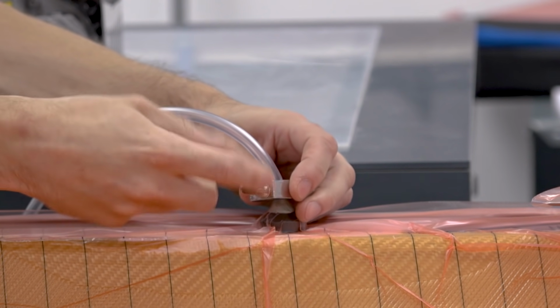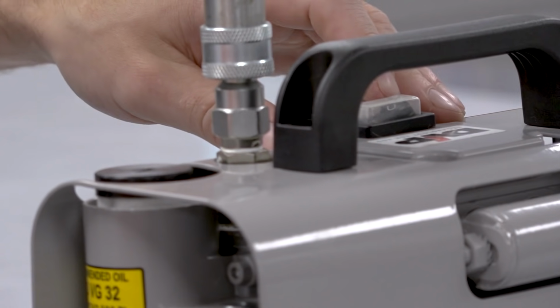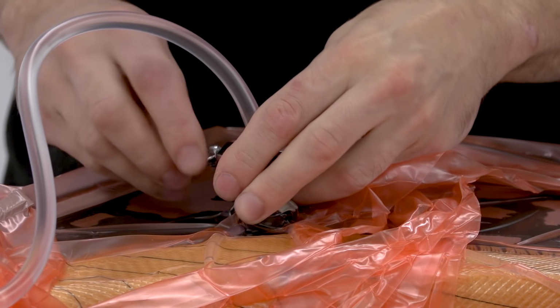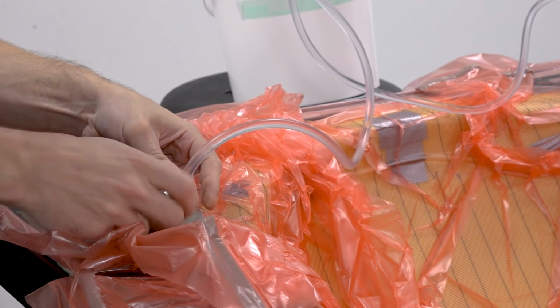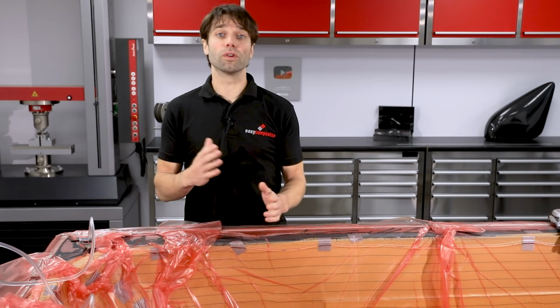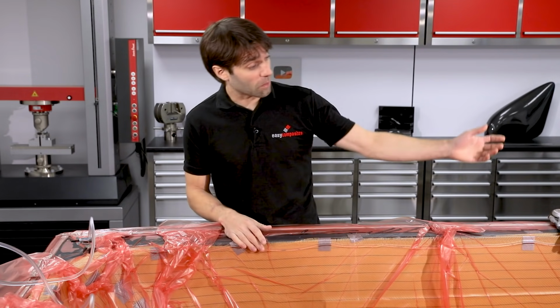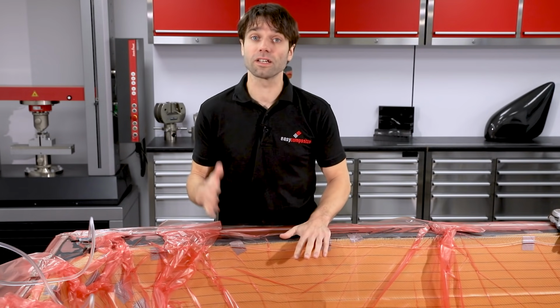With the part fully infused with resin, we can clamp off the vacuum line and switch off the vacuum pump. In this instance, we need to wait a few minutes longer for the correct amount of resin to be consumed by the part before clamping off the feed lines. This has now been left at room temperature for 48 hours to reach full cure, so we're ready to strip off all of the bagging materials and demould.